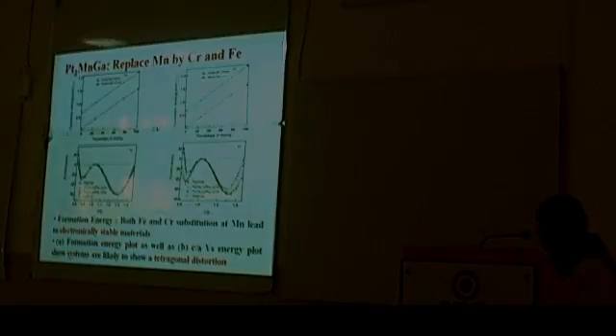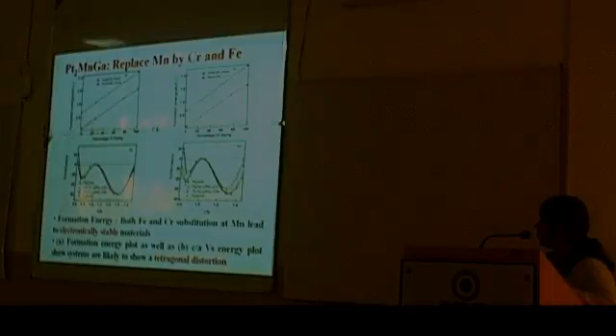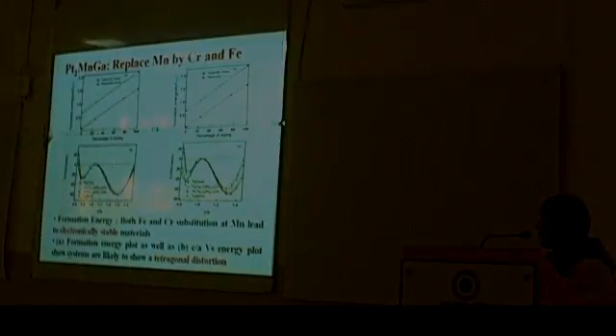We see that here, if you look at the stability, these are much more stable compared to the previous one which we can see here. Here the energy differences between the cubic phase and the martensite phase is not that much.